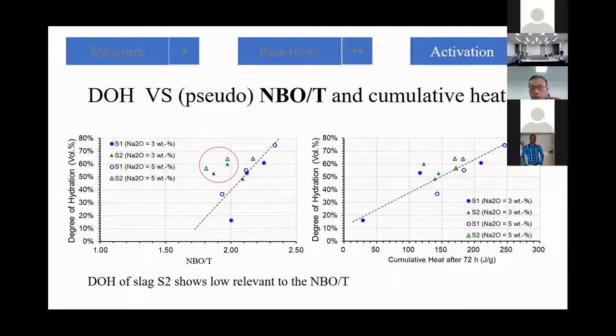But our parameter used to describe the degree of hydration does not work very well. It again indicates that in the presence of the silicate activator, it will influence the degree of hydration not just through the dissolution, but also through the reaction products.